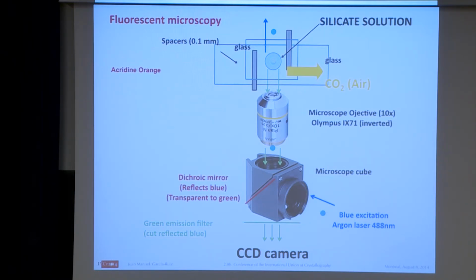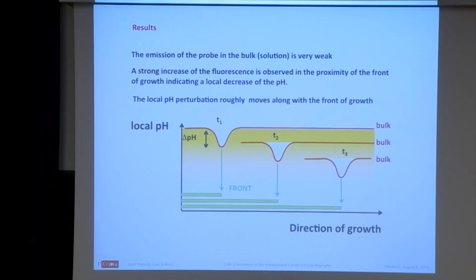So we did it with a colleague from Bologna using fluorescence microscopy. I will go faster on this because the point is basically that this is a wonderful technology, so that you can find and measure the variation of pH locally in a few microns, right? And very fast and with a very high pH precision. It was very difficult to obtain this kind of video because we had to avoid any complex shape, right? That would kill the measurement, right? So we have this. Let me just show again.